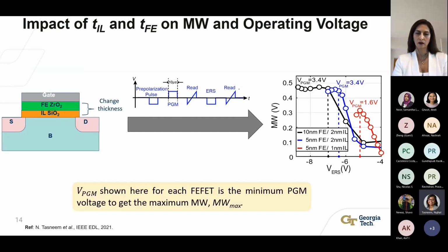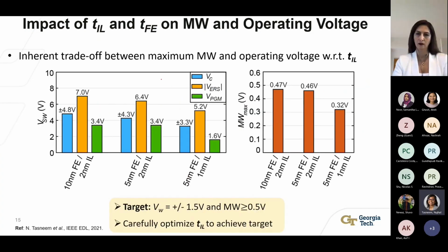For this experiment, we fabricated 3 FeFETs with 3 different gate stacks: a 10 nanometer ferroelectric layer with 2 nanometer IL, a 5 nanometer Fe layer with 2 nanometer IL, and a 5 nanometer Fe layer with 1 nanometer IL. We applied the standard memory window characterization technique, which is applying a program pulse and reading the device, then applying an erase pulse and reading the device again, and extracting the memory window from it. We applied it on all 3 devices. The memory window for a certain program voltage and varying erase voltages for the 3 devices is shown in this figure.